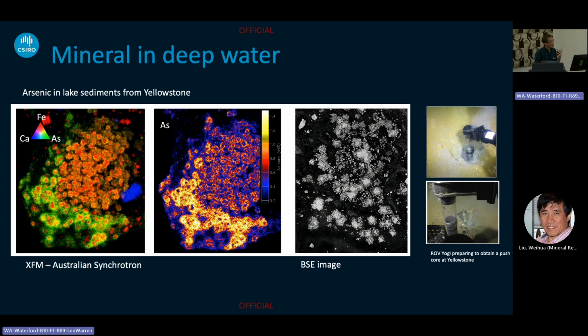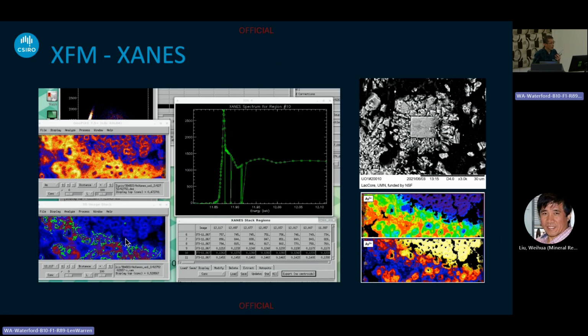This analysis has been done at the X-ray fluorescence beamline at the Australian Synchrotron. If you compare to that BSE image, the backscattered electron image, you can see that the power range of the synchrotron is bigger because the strong X-rays can penetrate the sample really well. So something that is buried below the surface, you can really see through it with synchrotron. So that's really very useful.